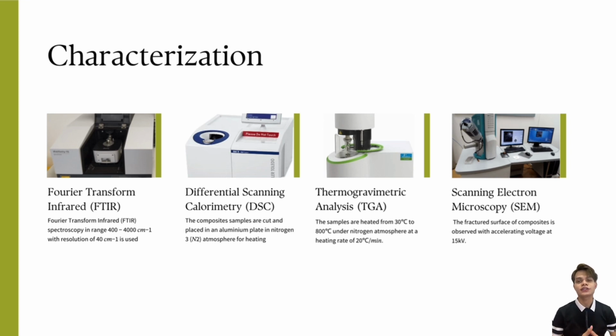The thermal stability and degradation temperature of the composite are analyzed using a thermogravimetric analyzer. The samples are heated from 30 to 800 degrees C under a nitrogen atmosphere at a heating rate of 20 degrees C per minute. The morphology of the composite will be analyzed using SEM. The fracture surface of the composite is observed with an accelerating voltage of 15 kV. Samples are sputtered with gold prior to observation to avoid surface charging during the test.